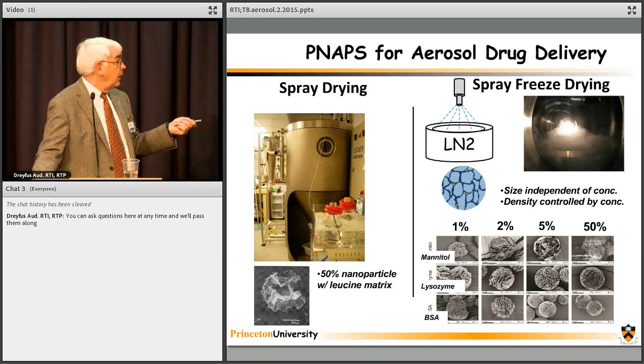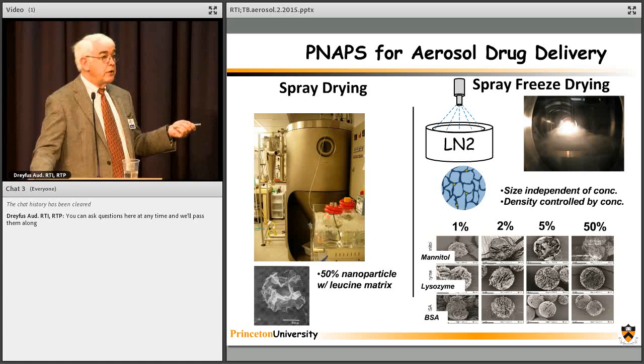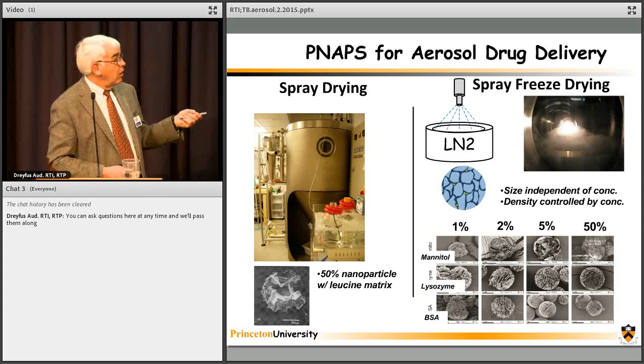And these are all spray dried under conditions where you have about 20 micron droplets, which then freeze. You then take that frozen material, you lyophilize it, and now you're lyophilizing all the water out. And so you can see they all have essentially the same particle size, but their densities are different.